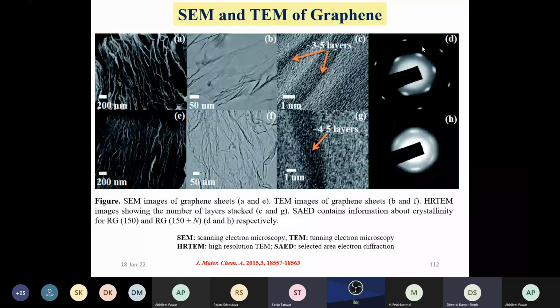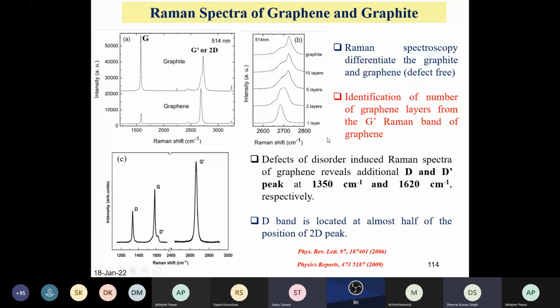After that, you can apply SEM and TEM images to verify how many layers are present in your carbon-based material, 3 to 5 layers or 4 to 5 layers. Further, the most important characterization technique for carbon-based material is Raman spectroscopy. You can differentiate the number of layers in your carbon-based nanomaterial using Raman. Raman gives information at certain peaks in terms of vibrational spectra. Generally, every peak comes from some molecular vibration like symmetric stretching, chemical bonding, ring breathing, or some other type of vibration. Every material's vibrations come from its structure, and every structure has its own peak in Raman. In simple words, Raman spectroscopy gives a chemical fingerprint, or chemical identification, of any molecule and material.